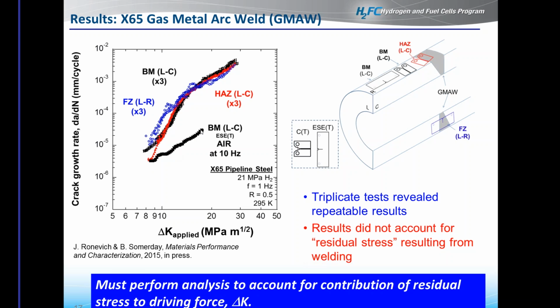The terminology of hydrogen accelerated fatigue crack growth really comes from, if you look at these lower delta K regions, you can see the 3 different microstructural regions we tested were the fusion zone, base metal, and heat affected zone. And you see that the crack growth rates begin to accelerate at these lower delta K regions. And this is where the terminology hydrogen accelerated fatigue crack growth comes from.